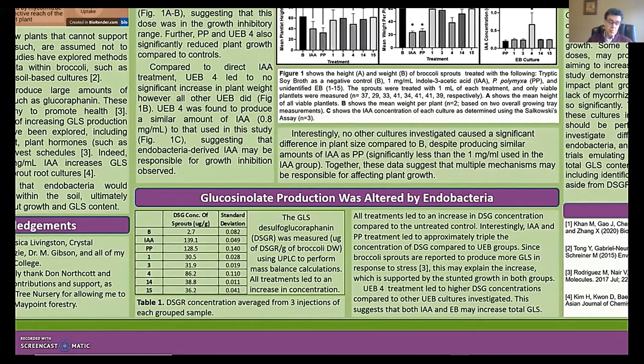Most of our UEB cultures, 1 through 15, were able to increase the disulfoglucoraphanin concentration to around 30 micrograms per gram, and UEB4 increased it to around 86.2 micrograms per gram. It is likely that UEB4 was able to increase the DSGR concentration so much more due to the increased amount of indole acetic acid that the culture produces.